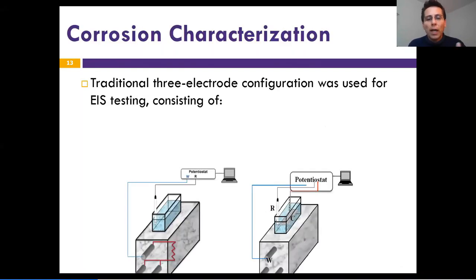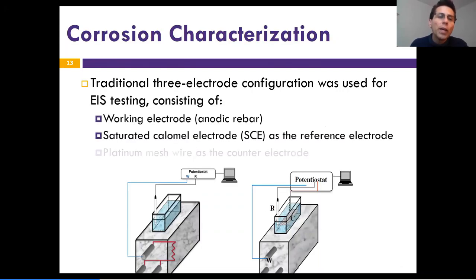The corrosion characterization was, again, based on the electrochemical system. We set up a system to send an AC signal, which is a non-destructive evaluation, and to see the response of each one of the concentrations of the microcapsules. We have this configuration in which the working electrode is the rebar. For the reference electrode, we use a saturated calomel electrode, and we use a platinum mesh for the counter electrode. We need a three-electrode system.